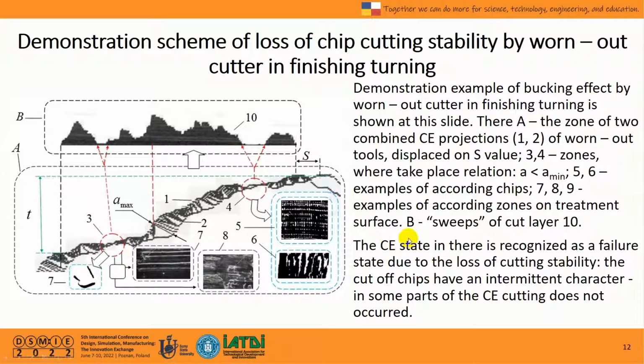There is A, the zone of two combined cutting edge projections displaced by S value. Zones 3 and 4 are where A is less than A minimum. Zones 5 and 6 are examples of chips. 7 and 9 are examples of the zone of treatment. B, sweeps of the cut layer 10. The cutting edge state is recognized as a failure state due to the loss of cutting stability. The cut of chip has an intermittent character. In some parts of the cutting edge, cutting does not occur.